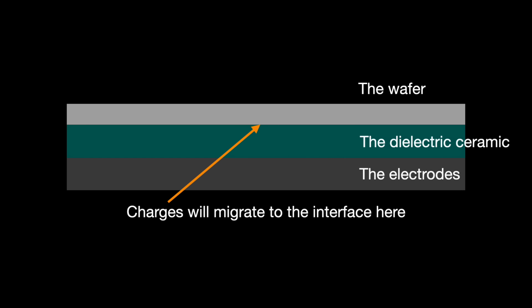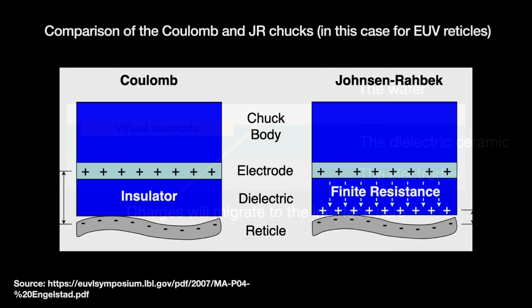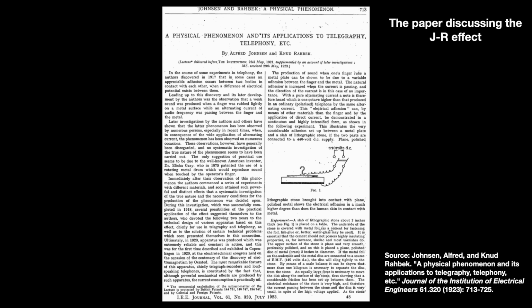Well, if the dielectric is just leaky enough, then a small amount of current can migrate through the bulk of the dielectric to its surface, the part interfacing with the wafer. This turns that dielectric interface surface into a virtual electrode located just micrometers from the wafer. We now have two opposing charges very close together, creating a powerful clamping force that cannot be achieved with only Coulombic-based forces. We call this the Johnsen-Rahbek, or JR effect, discovered and named after two Danish engineers in the 1920s. IBM had worked on variants of this since at least the late 1950s.